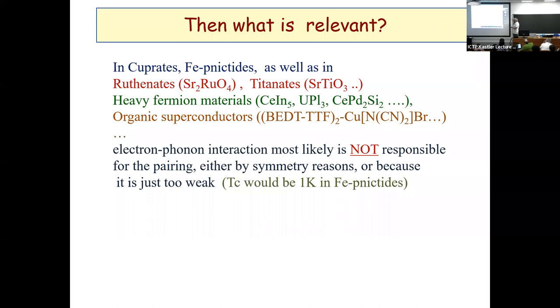And I guess one good example here is really iron-based materials, in which at the beginning of this iron-based era, people like Igor Mazin and his collaborators calculated the best case scenario for electron-phonon superconductivity, and found 1 Kelvin. Since then, they moved the temperature up, but it's still not 60 Kelvin. It's still at least an order of magnitude small. Let me take this as a premise: suppose that electron-phonon interaction by one reason or another is not the mechanism for superconductivity.